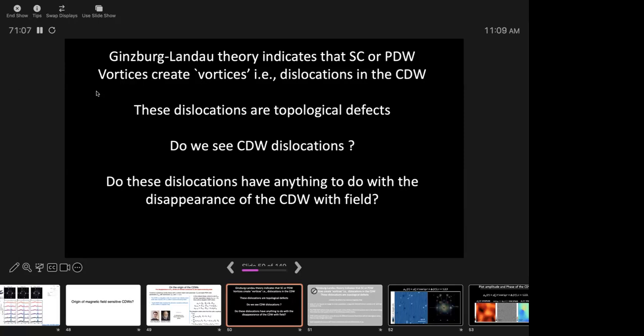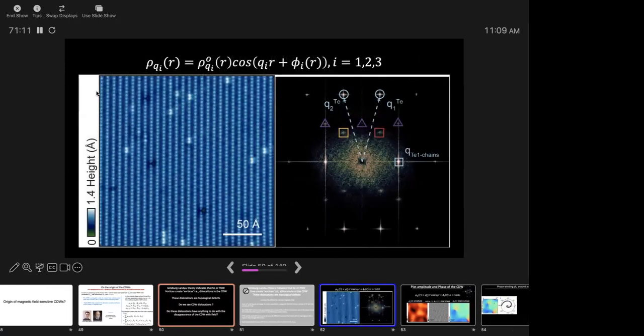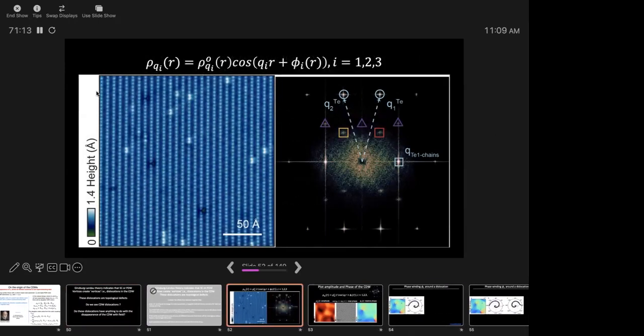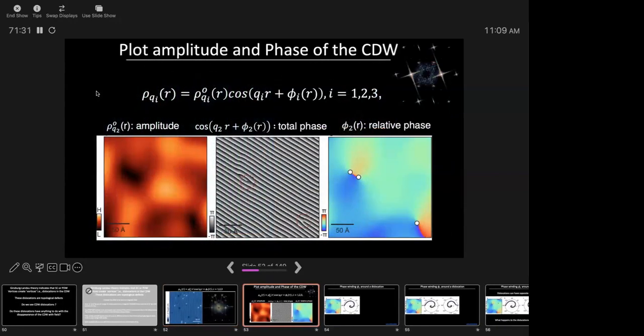So can we see these dislocations? Do they have anything to do with the disappearance of the charge density wave? Fortunately, in STM, when you do a Fourier transform, you have access to the amplitude of the order parameter, the charge density wave, but you also have access to the phase of the charge density wave. So you can extract that from the Fourier transform quite easily. Let me actually show you what that data would look like.